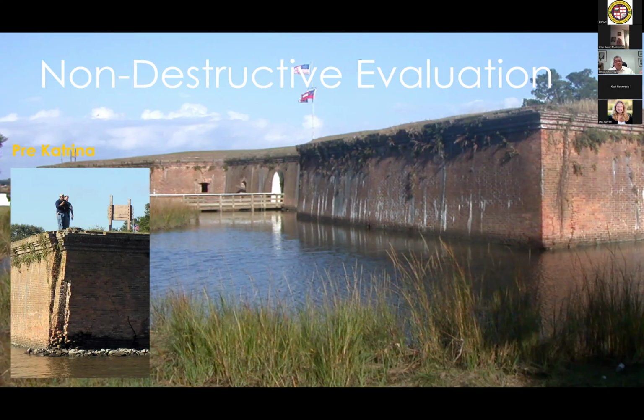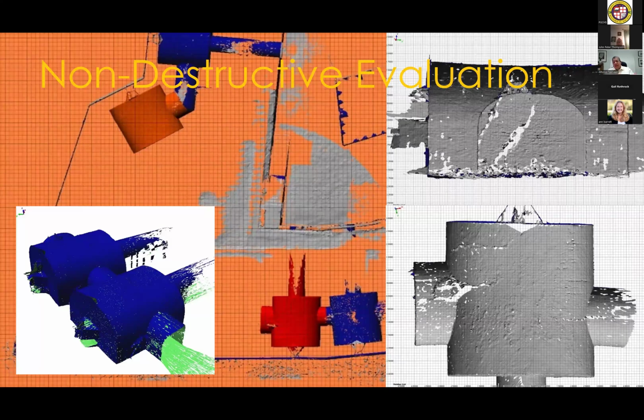We did our investigation. This is laser scanning that we've done inside the fort casemates. So you can see the outside of one of the corners, and then the inside are these casemates. Each color represents a different laser scan. That's why they look different. But you can also see in the right-hand side that the vault is sway backed at top. That means it's flattening out and settling, and is eventually going to crack and fail.